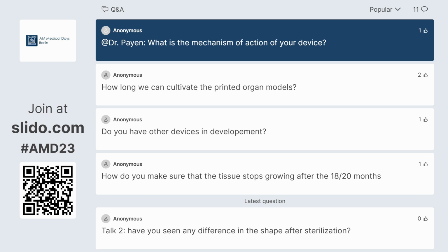One is mechanical, because the implant creates a protected space to allow the growth of the fat flap without the compression of surrounding tissue. And the second is biochemical, because it induces an acute and transient inflammatory response, which mimics a wound healing process. And there's a local production of angiogenic and adipogenic factors that fill the fat flap and allow the growing.